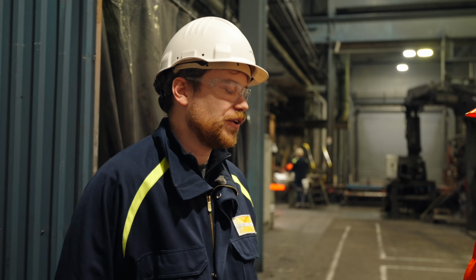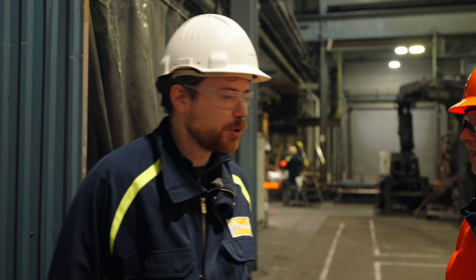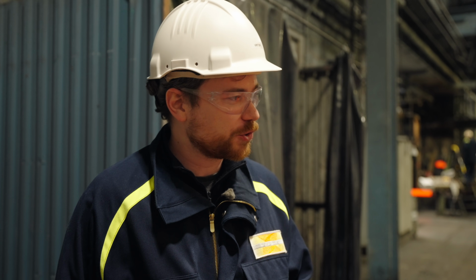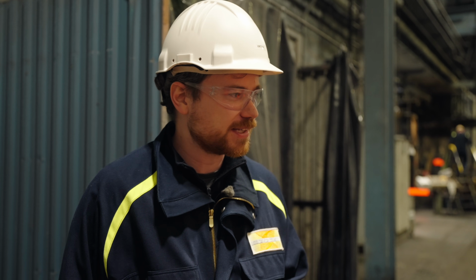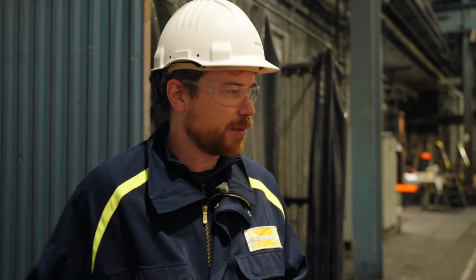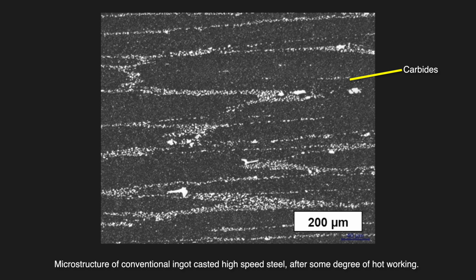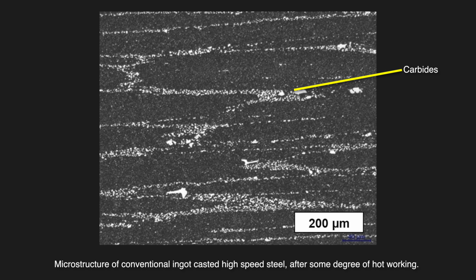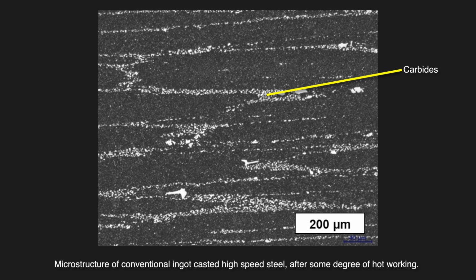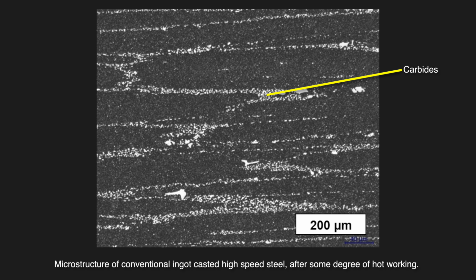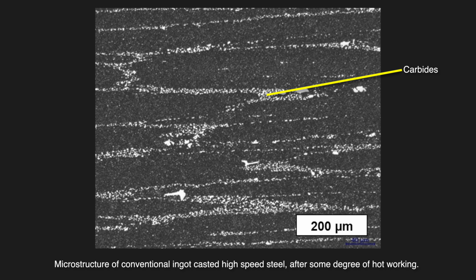First of all, we make a very highly alloyed product. You wouldn't actually be able to make most of the grades we make without making it into powder first. If you try to ingot cast these highly alloyed grades, the problem is that they will basically disintegrate when you start to forge them because there's so much segregation within the steel. You have all the alloying elements pooling together and forming clusters of carbides that make the steel, or the ingot in this case, extremely brittle.